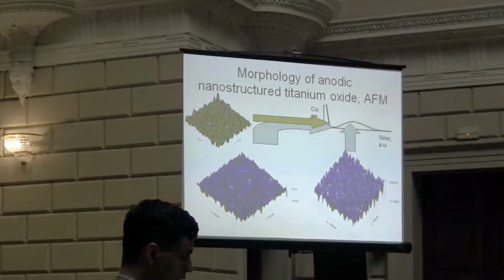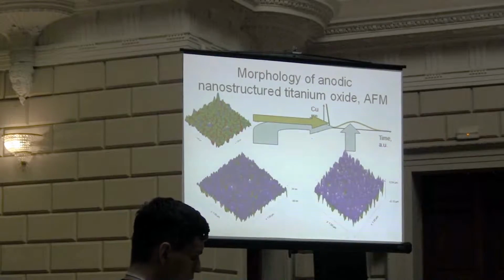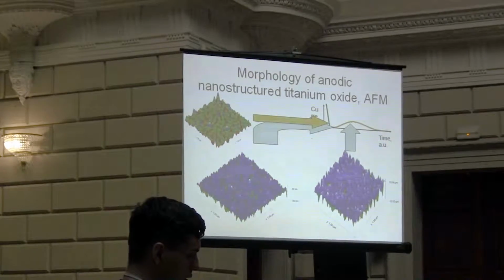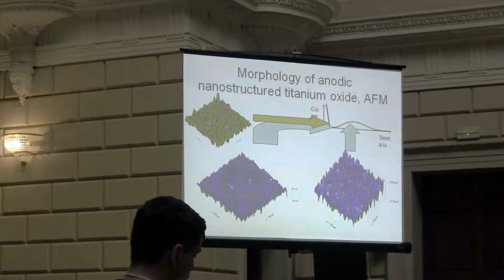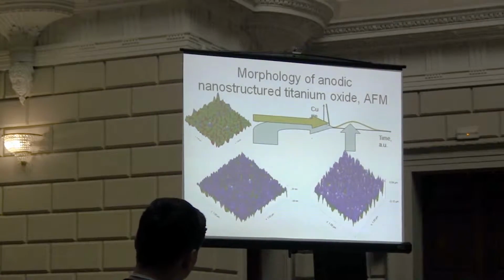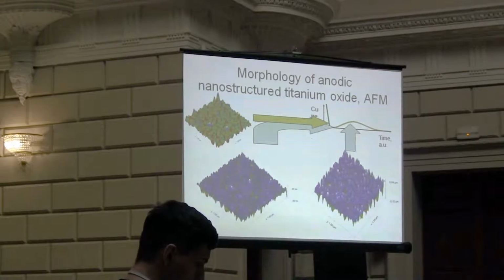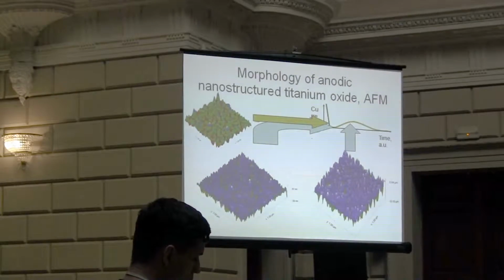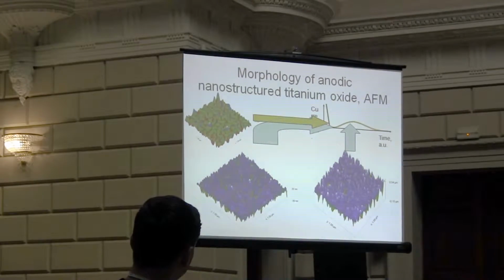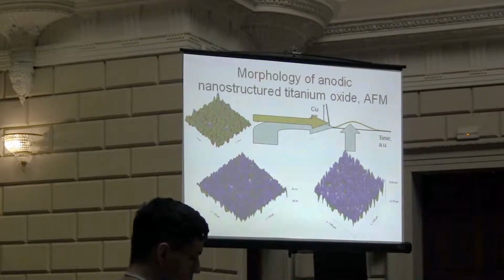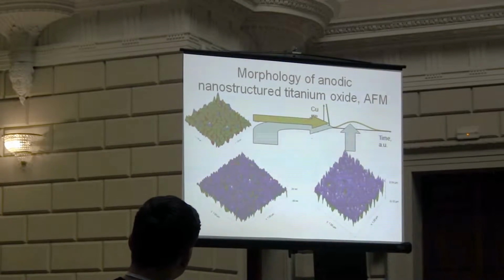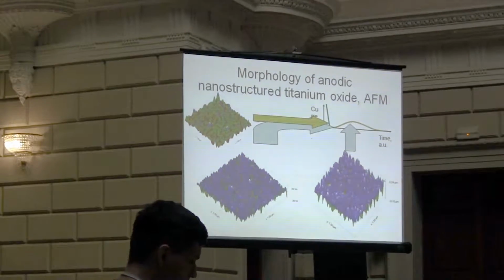On the next slide, the data of atomic force microscopy is presented. There are three junction points of the surface morphology, showing their position on the curve. Near the point A, the curve relief accounts for about 5 nanometers. As the branching of channels begins, in the next picture, relief accounts for about 30 nanometers and then up to 100 nanometers.